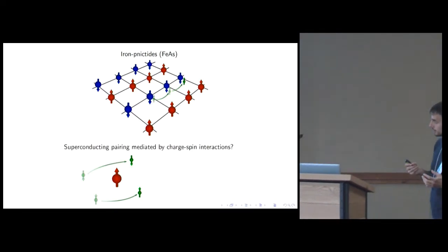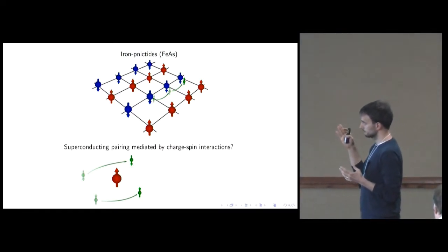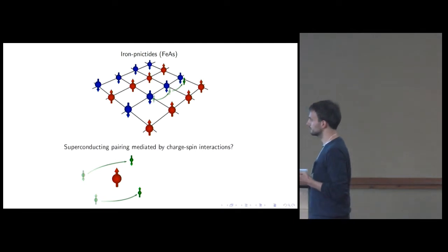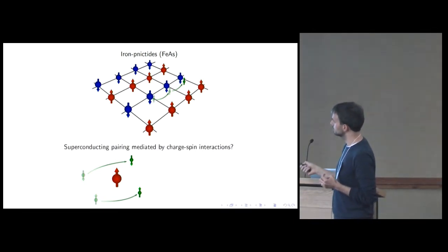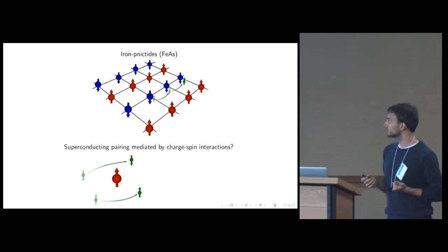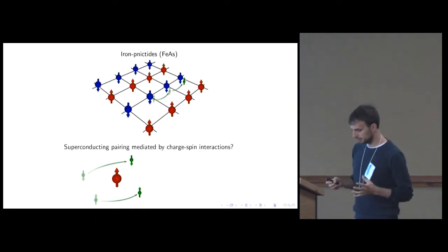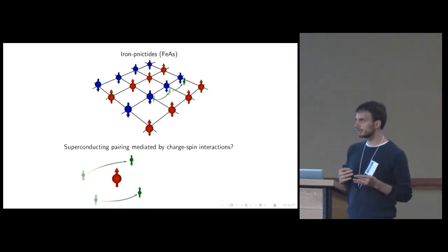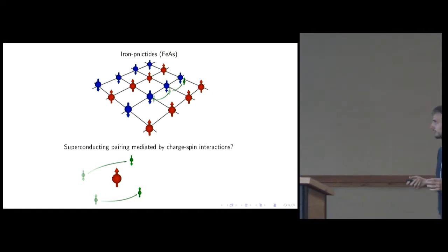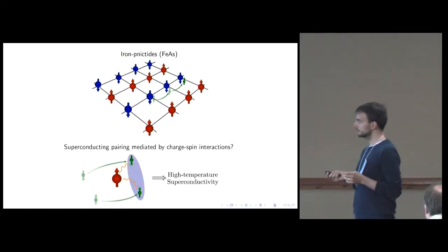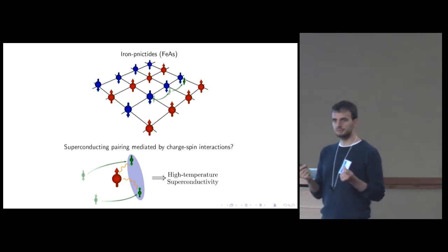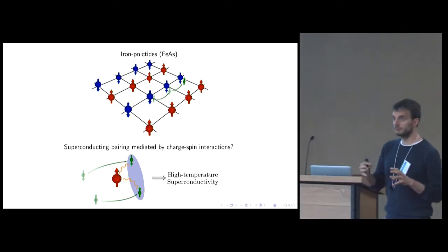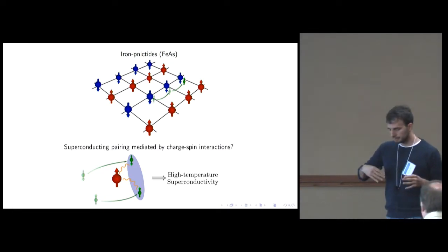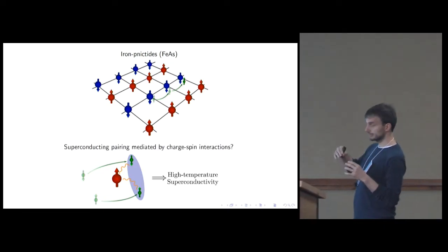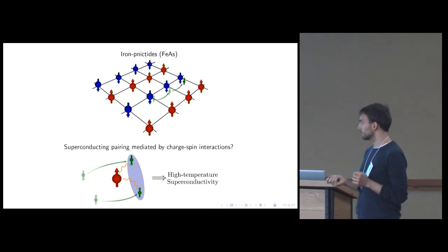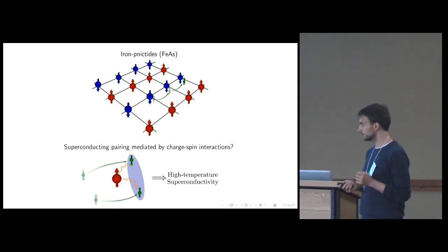We also have another situation in these materials. Most of these materials from this family are high temperature unconventional superconductors. And the community these days is more or less in agreement that the pairing between electrons in these kinds of materials is mediated not by phonons, like in conventional superconductors, but instead by magnetic excitations between these electrons and the local magnetic moments.